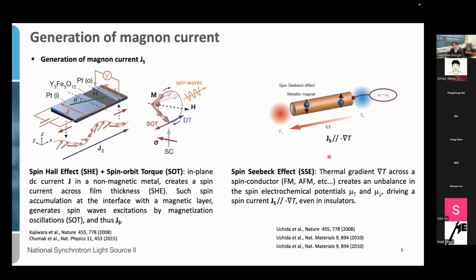Another approach, which I represented to the right, is by the spin Seebeck effect. So here, similarly to the regular Seebeck effect, we are dealing with a temperature difference, or temperature gradient, across our now conductor, that is again a magnetic medium. And because of this temperature gradient, we now generate an imbalance in the spin electrochemical potential. And because of that, we are driving now a current across the material in the direction anti-parallel to the temperature gradient.